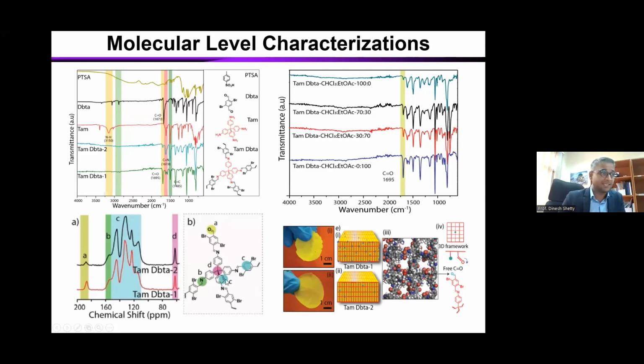Right? So then why would defects give hydrophobicity to the system? I think that is the basic question you may think. Obviously, I would love to explain it in detail, but in simple words, bromine is well known to introduce some hydrophobicity to the system. And also, when you have a bromine and a neighboring carbonyl group, you can have hydrogen bonding as well. So it's a synergistic effect, basically because of the defect area exposed to bromine as well as hydrogen bonding between them. It leads to the hydrophobic nature of the highly defective system, and on the other hand, hydrophilic nature of the other system.